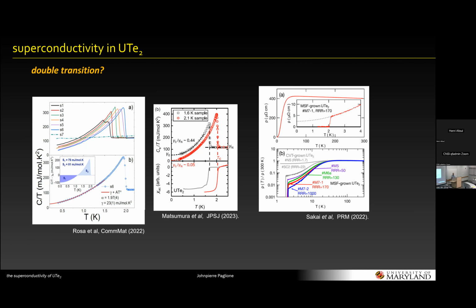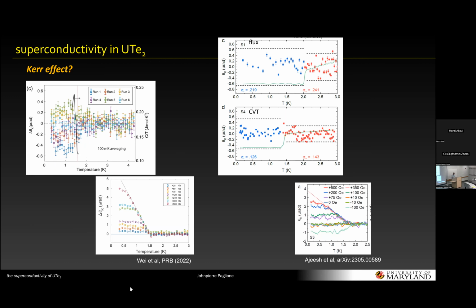Can the Kerr effect be due to just vortices? Yeah, so you can talk to Aaron about this, or he has a follow-up paper actually, this PRB paper, which goes in depth and does sort of the first type of analysis of this critical state model, to understand when the first vortex comes in. So in short, the way these experiments are done, you cool the sample in a field and then turn it off, and come up. So these are cooled in different fields, and then the field is turned off, and the measurements done coming up. So as you increase the cooling field, you get a larger Kerr signal. So this is cooled in 500 Oersted, turned off, and then you have more vortices.